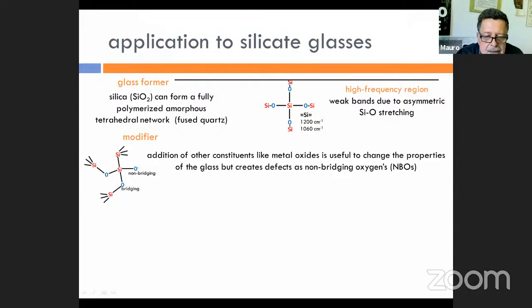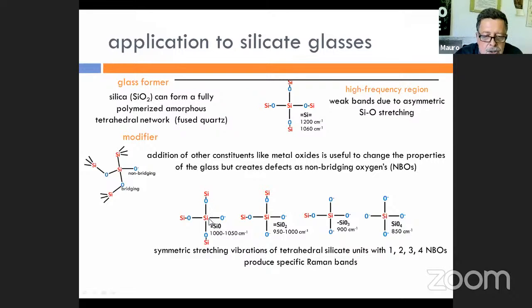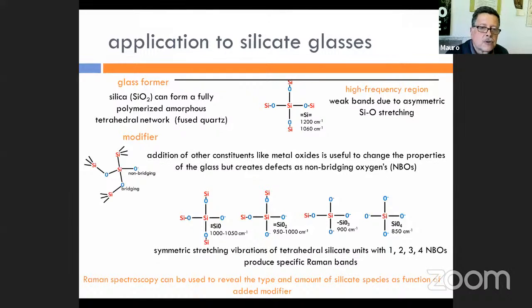Now what happens is that the silicon-oxygen stretching vibration frequency changes according to the number of non-bridging oxygen that are present in the tetrahedral structure. So you can see that if you have only one non-bridging oxygen, you have bands in this region, and with two non-bridging oxygen, there is a low frequency shift of the stretching frequency. So Raman spectroscopy can be used also in glasses to reveal the structure, and the structure changes due to the addition of the modifier.